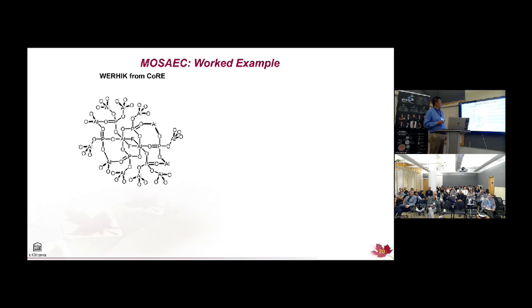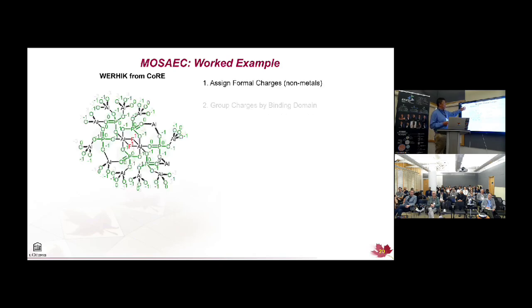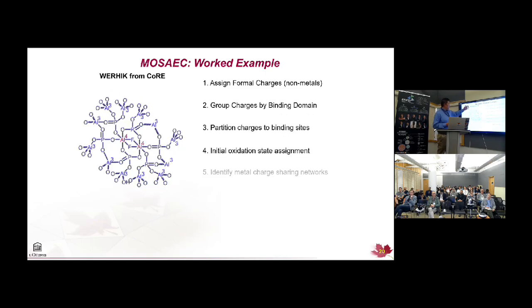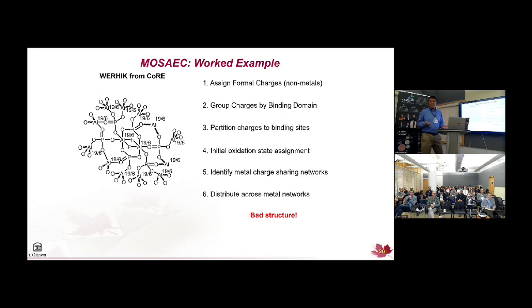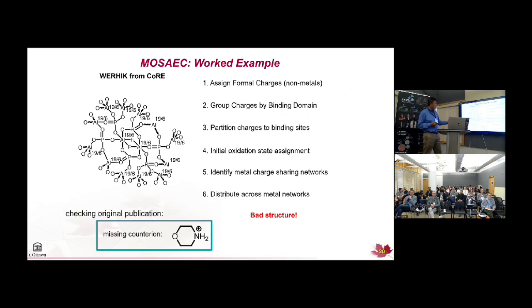You can do the same thing for a bad structure. This aluminum one, again I won't go through it in detail, but the whole thing shares charge. And so you end up with non-integer charges, which is an indicator that it's a bad structure. And indeed, if you go to the original publication, they didn't account for the counter ion.